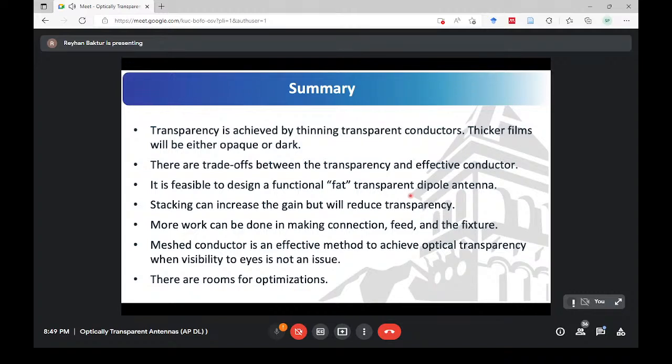Now, to make a transparent conductor, or any transparent conductor, it is basically just a very, very thin conductor. Because they are so thin, they are limited by the microwave skin depth. If the material is thinner than the microwave skin depth, then the material is going to be very lossy, and therefore the antenna is going to be not efficient, right? So another route to go is to mesh the conductor. So when you mesh it,